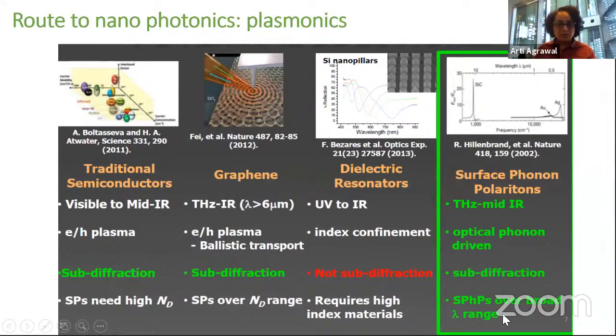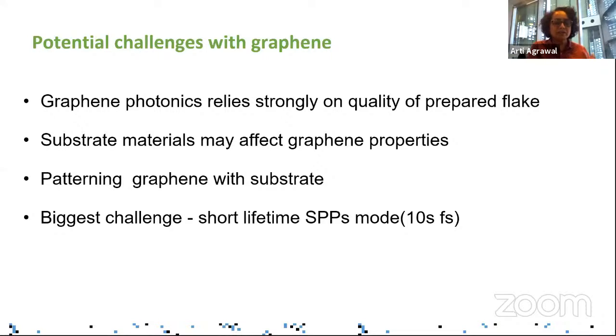Now, let me sum up some of the issues regarding graphene-based plasmonics and surface phonon polariton plasmonics, and then see where we are headed with this. So the potential challenges with graphene are that graphene photonics relies very heavily on the quality of the prepared flake of graphene. And depending on the substrate material, that affects the properties of the graphene as well. So if the substrate is not done properly, or if the flake is not well prepared, this is going to impact the quality of the material. It's going to impact its properties. It's also very difficult to pattern graphene with substrates. And as I've said before, one of the challenges is that the lifespan of the SPP is not very long. So this is again an issue.